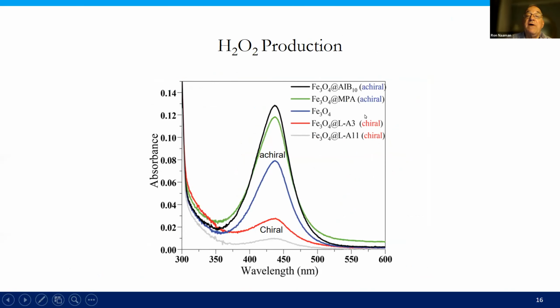Now, what about hydrogen peroxide? So when we have no chiral electrodes, we produce, this is the signal of hydrogen peroxide observed by putting some dye that is sensitive to the hydrogen peroxide. So you see here we get a strong peak indicating that there is hydrogen peroxide. Now, when we use an electrode that's coated with a short chiral molecule, you see immediately the amount of hydrogen peroxide decline. And when we use a longer chiral molecule, which is an even better spin filter, then it decays even more.